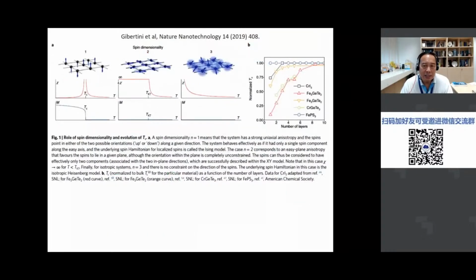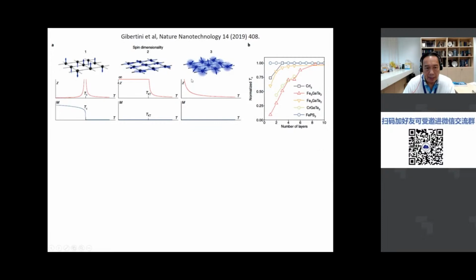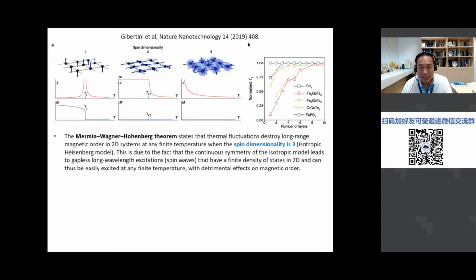So in the next slide, in their figure 1 in the paper, they explained it. So you see 3 classes of 2D materials with spin dimensionality 1, 2, and 3. So let's go. The Mermin-Wagner-Hohenberg theorem states that thermal fluctuations destroy long-range magnetic order in 2D systems at any finite temperature when the spin dimensionality is 3. And this 3 is the isotropic Heisenberg model. So the spins are able to point any direction. And in this case, thermal fluctuations will destroy magnetic order. So you don't see any Curie temperature. There's no transition to magnetic order in the spin dimensionality 3.